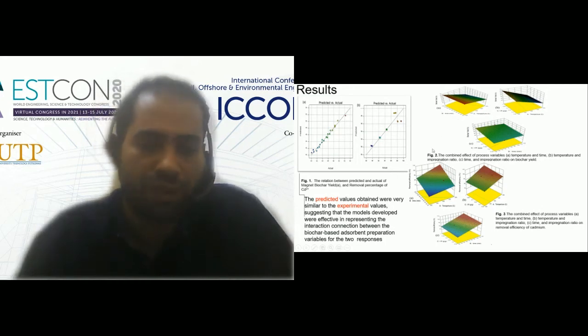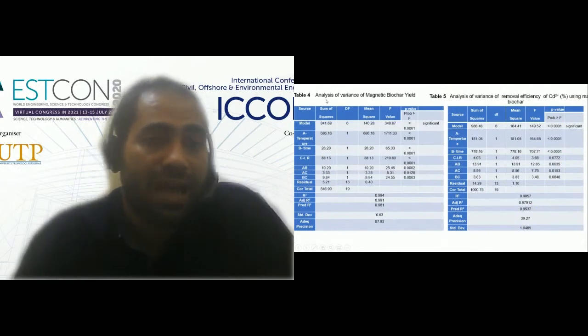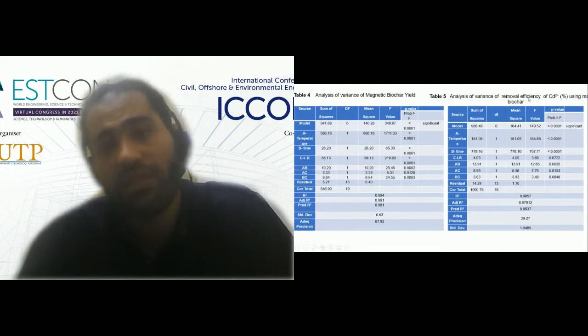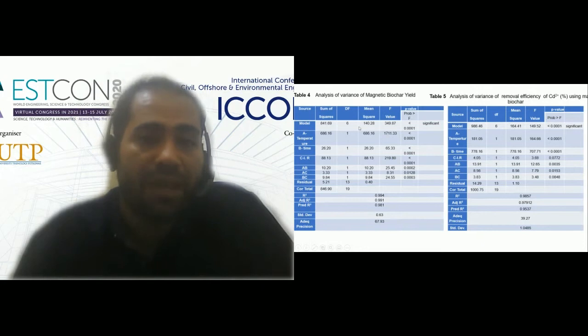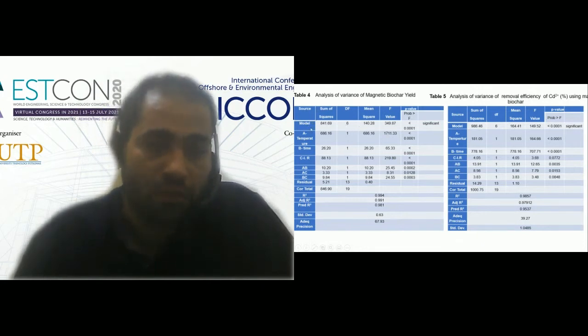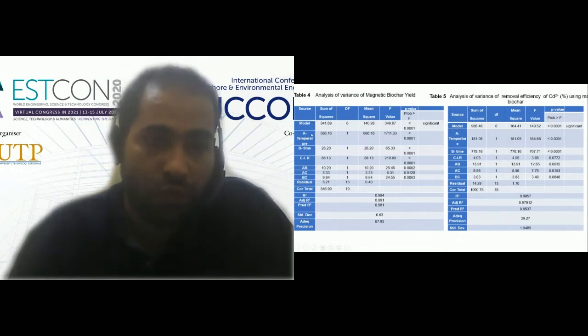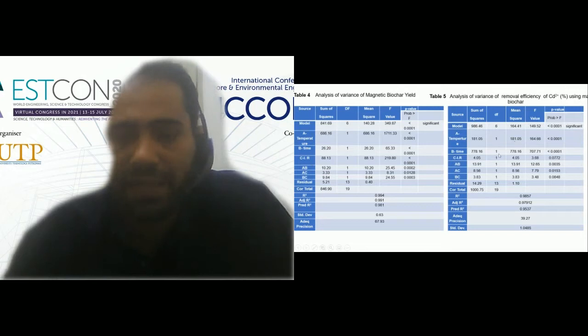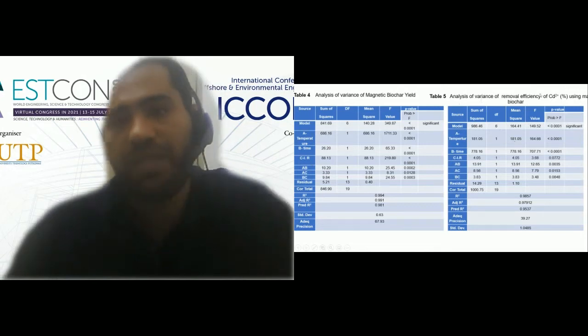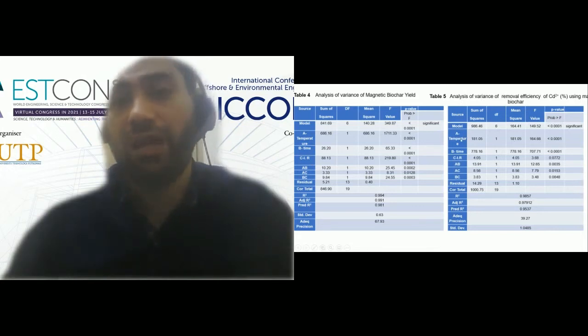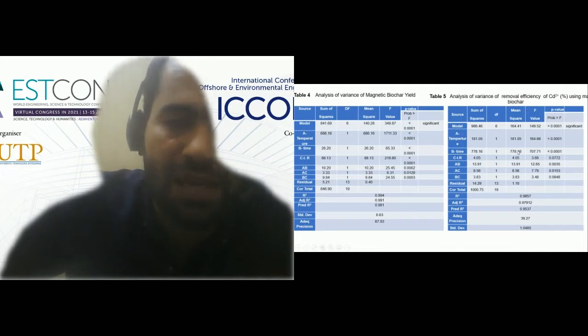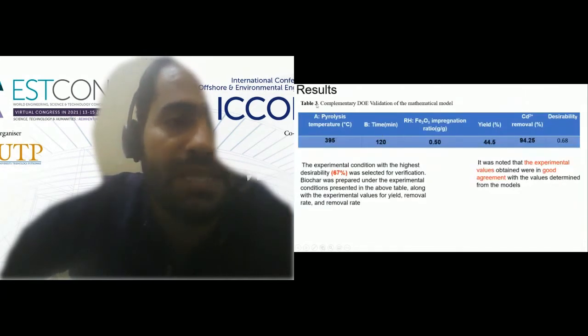We have two figures now: the analysis of variance of magnetic biochar yield and the analysis of variance of removal efficiency of cadmium. In the first response, the model was significant, and the two parameters, temperature and time, were significant, while the impregnation ratio was also significant. In the analysis of variance of removal efficiency, the model was also significant, and temperature and time were significant, but the impregnation ratio was not significant. But the impregnation ratio also gave added value to the biochar, which can be easily regenerated and separated.